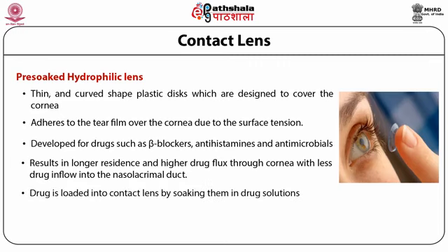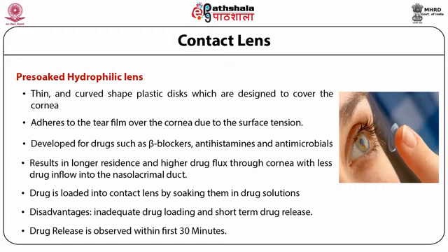Drug is incorporated into these lenses by soaking them in drug solutions. It is found that most of the drug is released within the first 30 minutes. This method, however, results in inadequate drug loading and short-term drug release. Also, the use of preservatives may result in toxic effects on corneal epithelium.